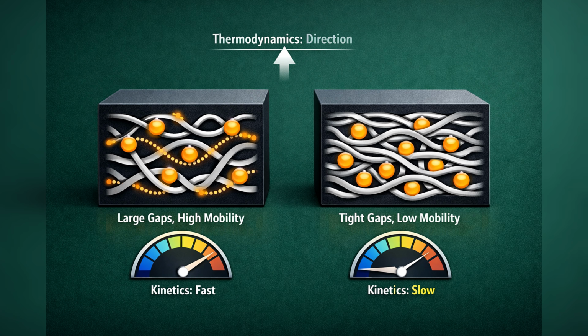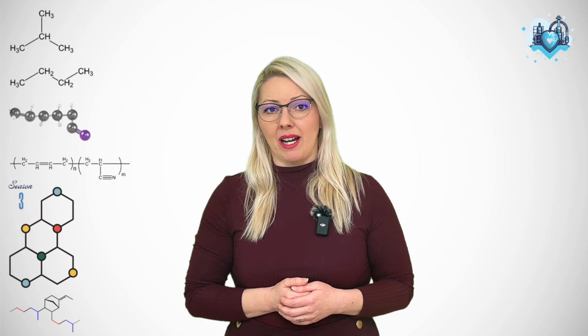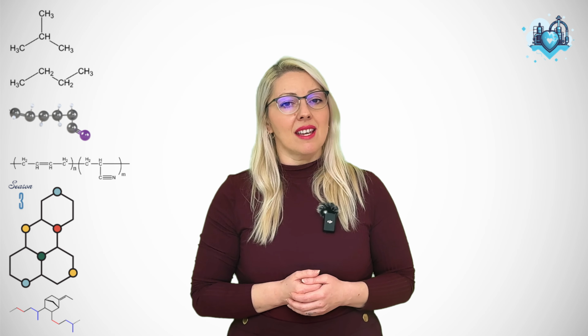On a practical level, diffusion is controlled by molecular mobility, compatibility, and free volume inside the rubber matrix. Oil molecules move by hopping through gaps created by polymer chain motion. If those gaps are large and mobile, migration is easy. If they are tight and restricted, migration slows down. Thermodynamics decide whether oil wants to move. Kinetics decide how fast it gets there.